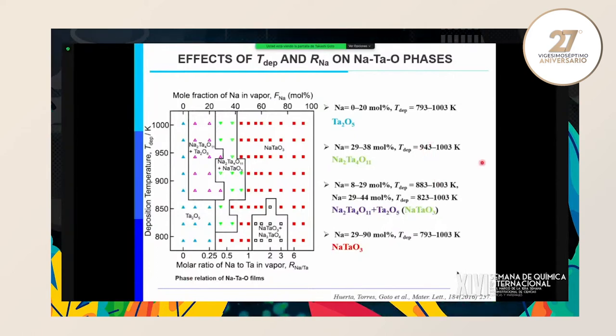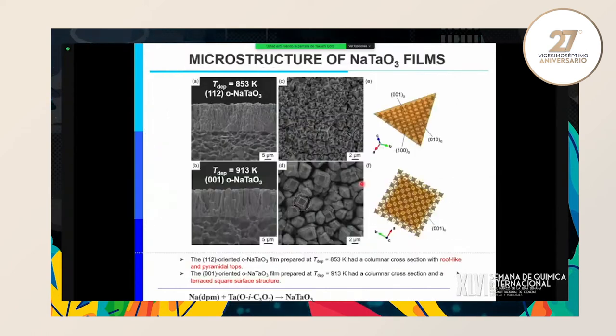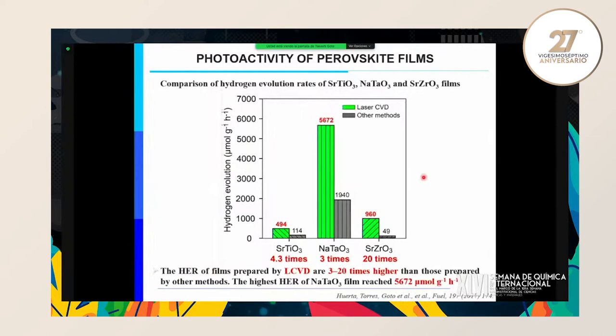Actually, this was done by Mexican student Ari. Thanks very much to Ari. And we can make very faceted, well-oriented sodium tantalate films in many kinds of directions. And we can make a very good faceted oriented film, and it shows very good performance. Sodium tantalate by laser CVD, very well faceted, shows about three times higher hydrogen evolution. Strontium zirconate shows 20 times. Strontium titanate shows about four times higher performance.